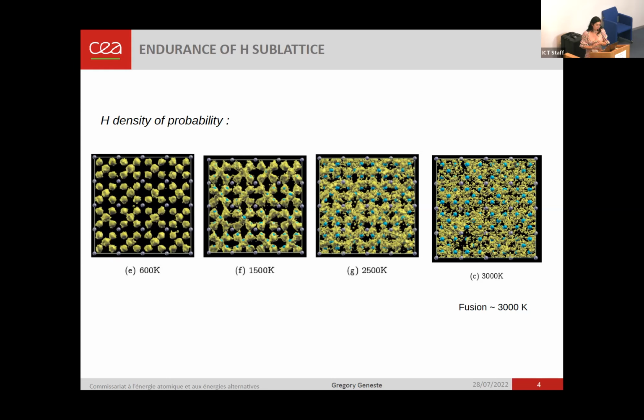at 1500 Kelvin, the hydrogen stays in the same place, and at 2500 Kelvin, the sublattice of hydrogen is still there. There's an endurance of the hydrogen sublattice, and when the compound melts at 3000 Kelvin, you can see that the hydrogen density is completely random; it diffuses completely like a liquid.